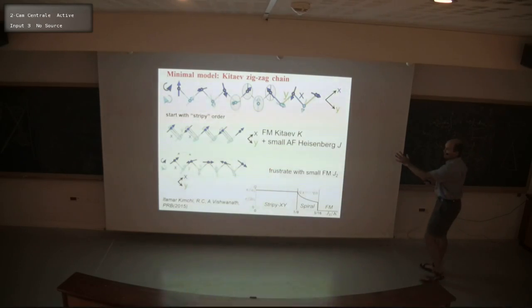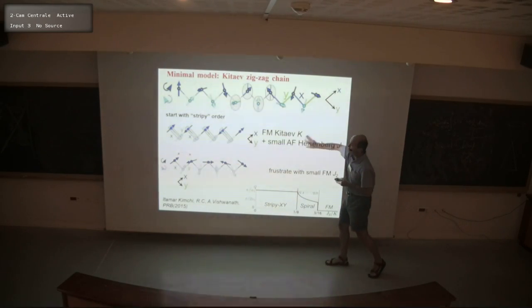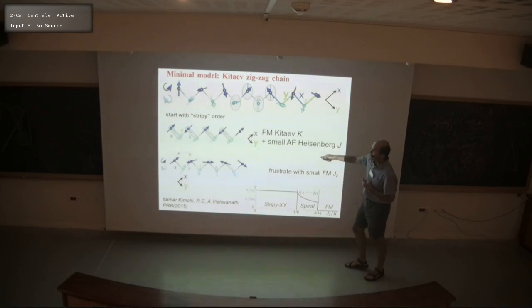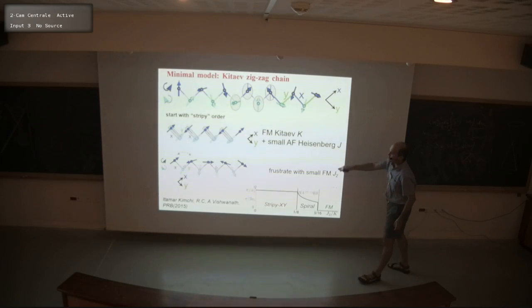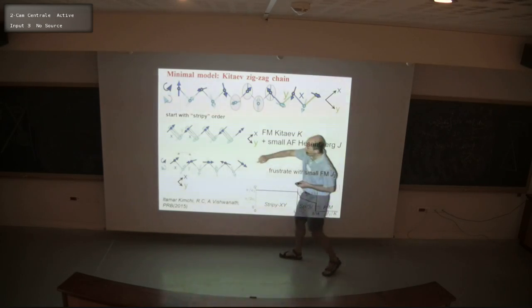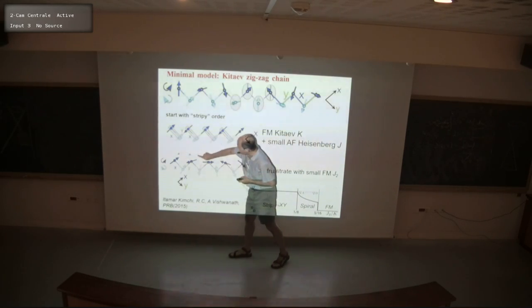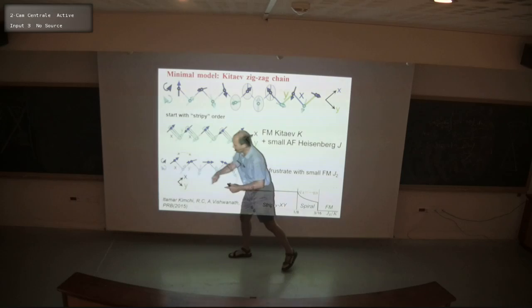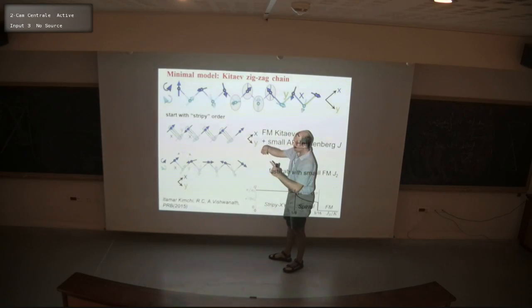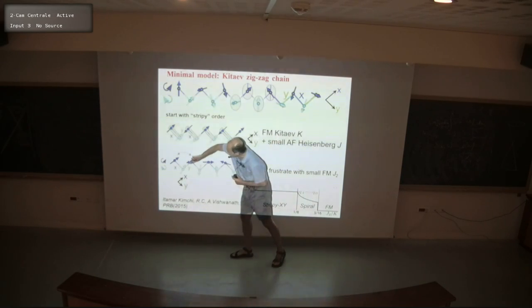Now, this is not what we see experimentally. Experimentally, we see some rotation that breaks this collinearity between the spins. And one way to do that is to add a second neighbor coupling that breaks this collinear orientation here. And so this is the key thing. So imagine that you've added an interaction that wants these two spins to be away from exactly antiparallel. So let's say this spin has rotated clockwise, this way.